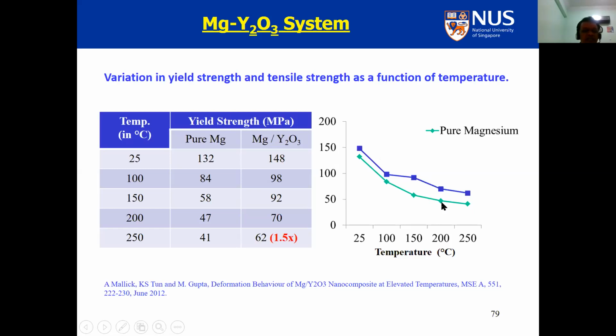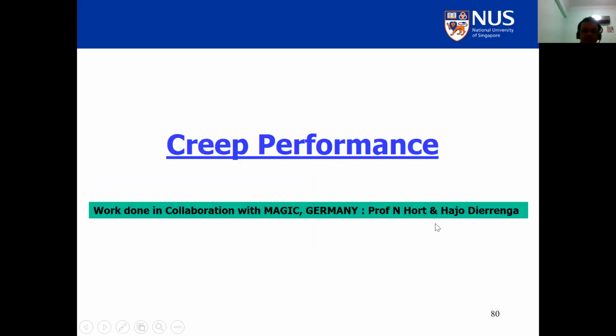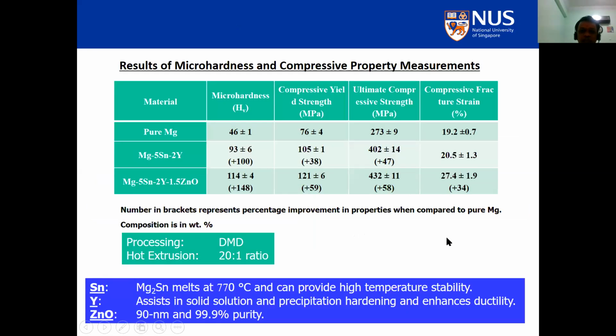So that means these materials will have a higher durability when compared to the monolithic material. To take it further, we also did some creep work in collaboration with researchers in Germany, Professor Hort and Hajo, and we gave them a new alloy in which we replaced aluminum by tin. Our results were positive: hardness goes up, compressive yield strength goes up, and the UCS goes up, ductility marginally goes up. Then we put zinc oxide particles, 1.5%.